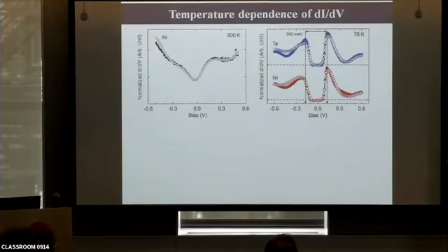However, considering the thermal broadening, it is more natural to assign the gap size as the peak-to-peak distance. So here, the peak-to-peak distance is 300 meV, which is the genuine energy gap in the excitonic insulator.